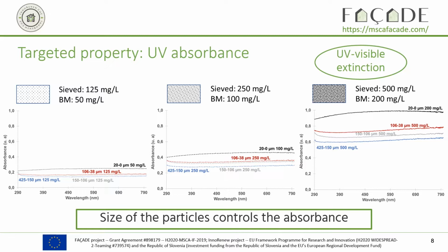However, we tried to use different particle sizes and to measure the UV absorbance. So we dispersed the carbon powder in different concentrations in water, and we measured the absorbance of the solution. So here you can see 4 different curves. You have 3 curves related to the sieved particles. Red is the smallest particle size, then gray, then blue. And the black one is a ball milled one.